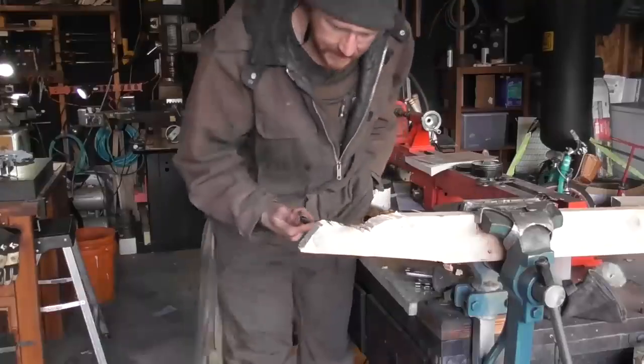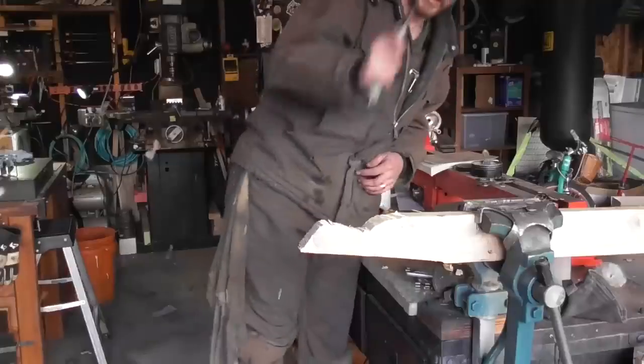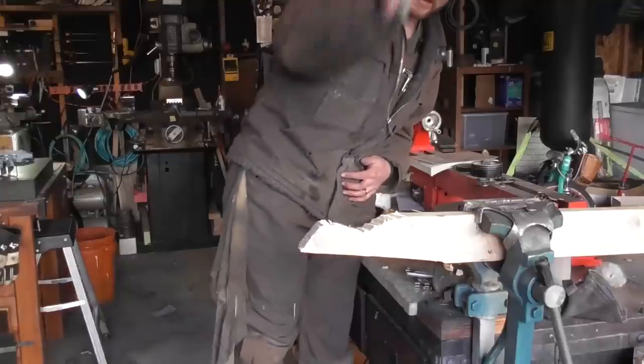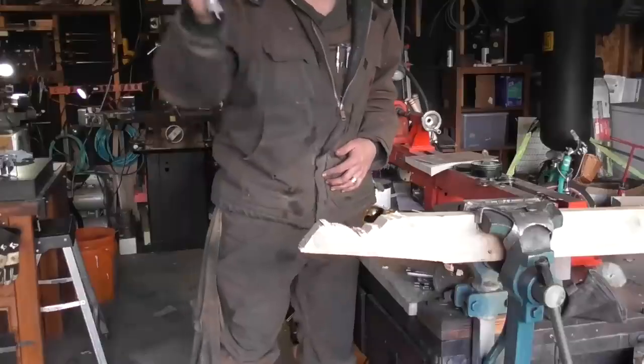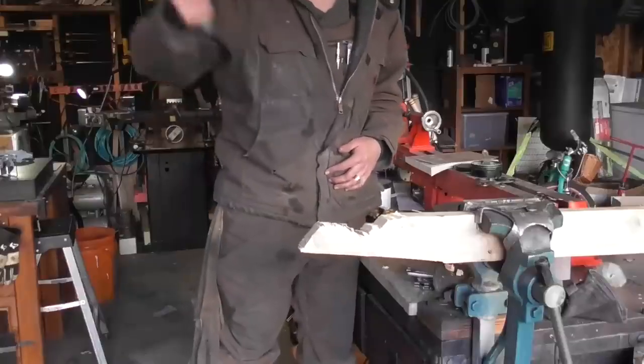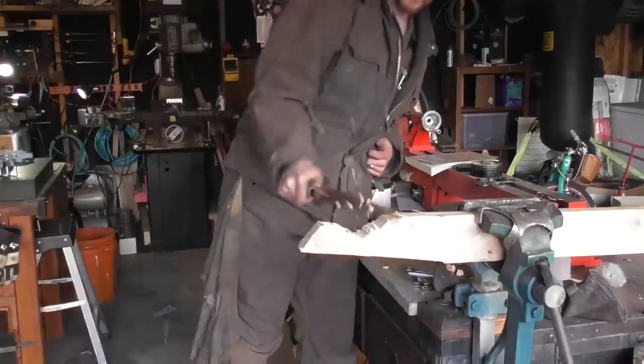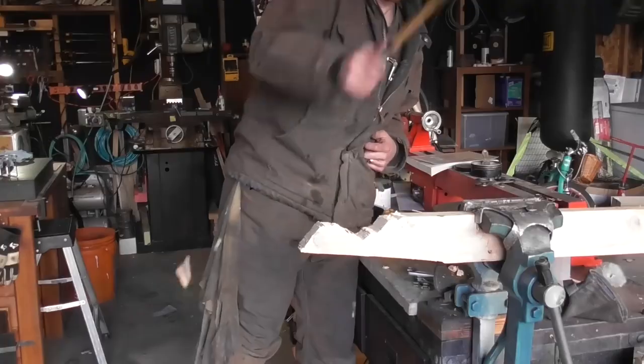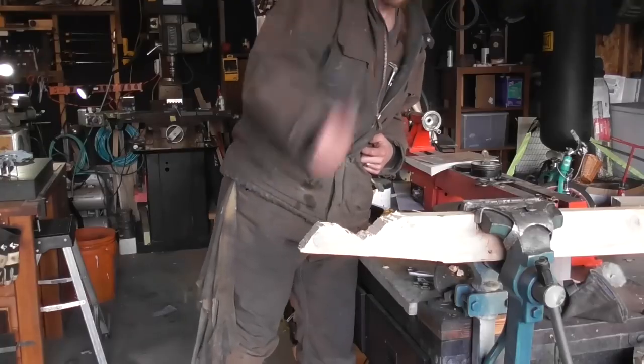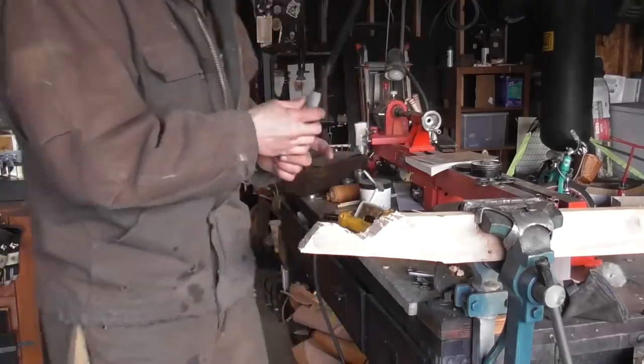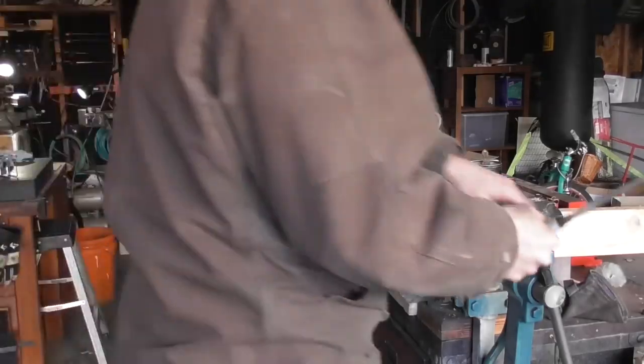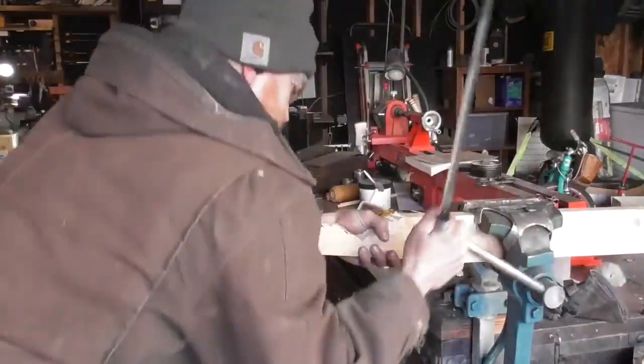So usually what I do is a 2x4 chop, and I kind of vary it depending on the size of the blade, the length of it, the thickness, all of that stuff. It's really like how much stress are you going to be putting on that edge to make sure that it holds up. And so this one I whacked through a 2x4 two times, and then you want to make sure that it's still shaving sharp after you do that test. That's how you know that you have both a good heat treatment as well as good edge geometry.